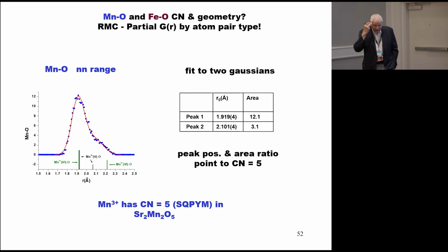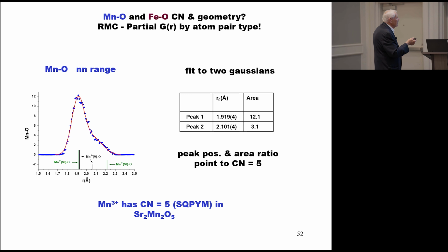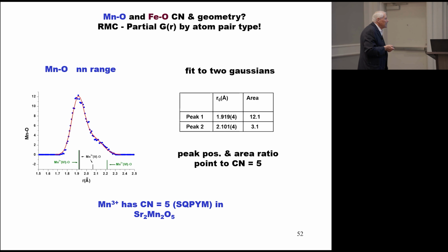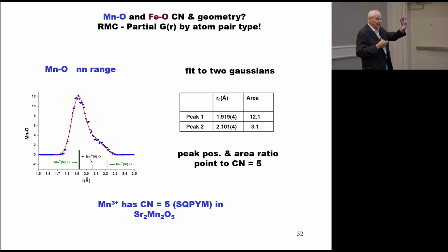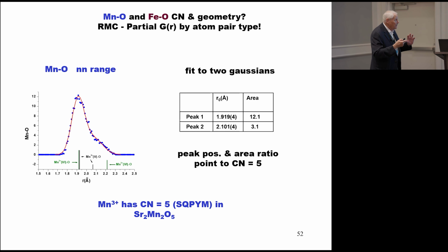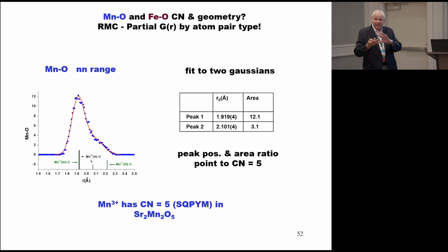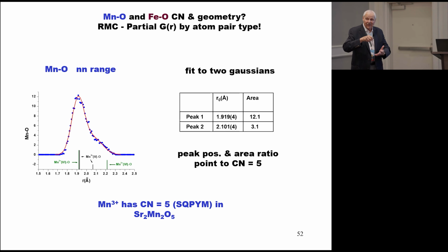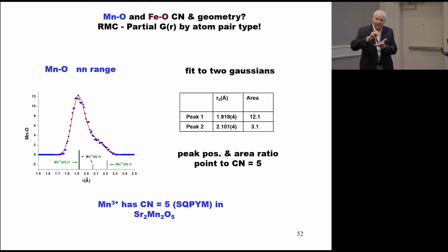One of the nice things about the RMC large box approach is that you can extract local or partial contributions. So you can extract the nearest neighbor bonding regime for manganese-oxygen and iron-oxygen. Remember, in the Brownmillerite, this is an octahedral site, a tetragonally distorted octahedral site. So you should expect to see maybe two peaks in a ratio of about 2 to 1, right? There's two axial and 4 planar. In fact, what you get is something like 4 to 1,